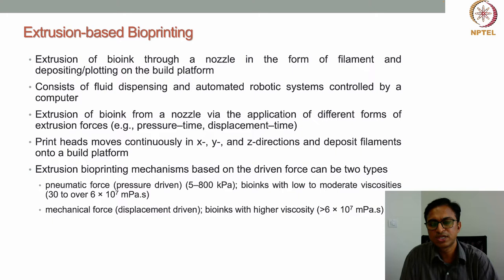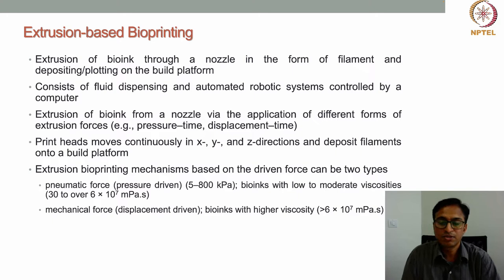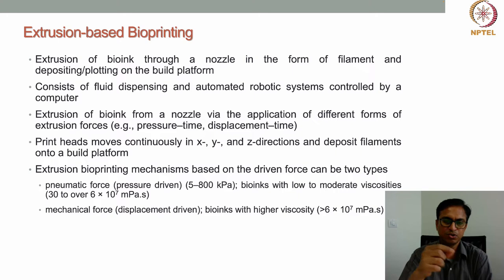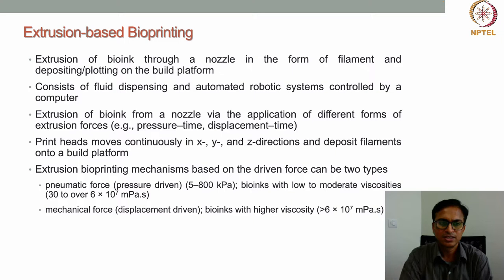The material used is mostly a polymer solution, a hydrogel, a nanocomposite, or other fluidic materials. That material is put into the fluid dispenser or inside the syringe, and then pressure is applied on top of the syringe so the material comes out through the nozzle. The nozzle dimension ranges from 100 to several hundred microns. The material comes out as a filament, which is deposited on the build platform to fabricate different types of structures.